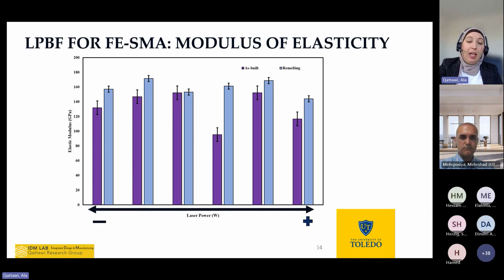The first one is reducing any microstructure defects that happened where the laser at the first pass couldn't sinter the powder. The second objective is to treat this material with the laser in order to get the bulk material that we need. This technique reduces the speed of production, but it still improved the modulus of elasticity for this specific alloy system. Now, one problem we found in this alloy system is the unpredictable brittleness of the material.